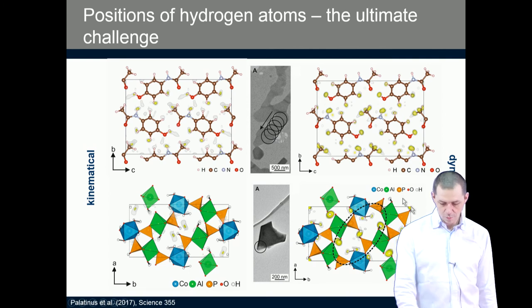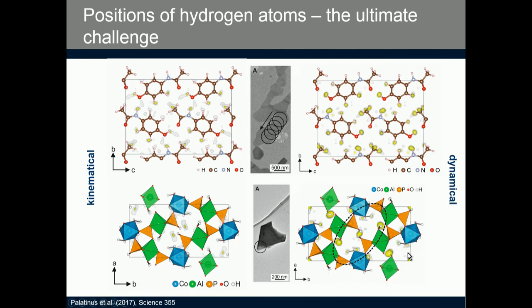And the same is true for the cobalt aluminophosphate, where again we can nicely locate the hydrogen atoms belonging to the water molecule coordinated to aluminum. And what is even more interesting, this structure contains a partially occupied cobalt site, which alternates with an orientation of hydrogen atoms that points into that cobalt place if there is no cobalt atom in there. So there are actually partially occupied hydrogen positions, and we could detect even these partially occupied hydrogens in the difference Fourier map.